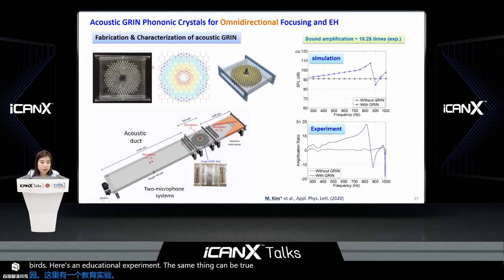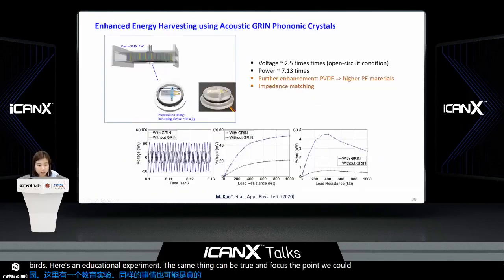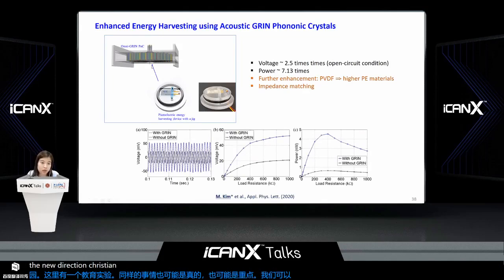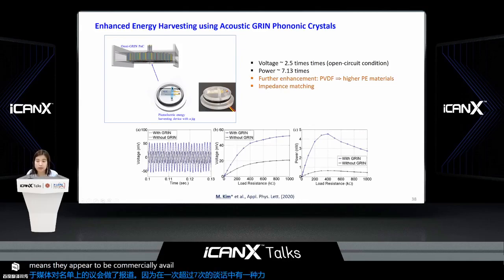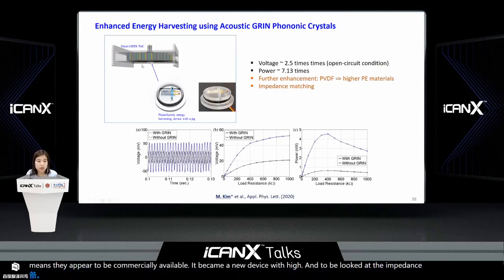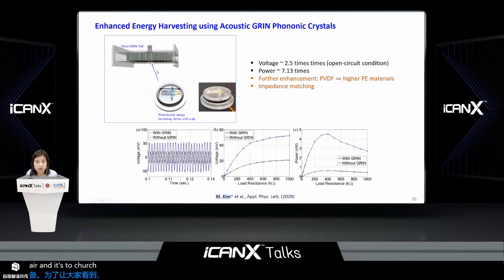And at the focused point, we tried to characterize the harvesting performance using these omnidirectional phononic crystals. So we located the PVDF, the piezoelectric polymer film, on the bottom of the omnidirectional phononic crystals, and we found that there's a power enhancement of up to more than 7 times. And since we use the commercially available piezoelectric polymer film, if you use a device with high performance piezoelectric material, there's room for further enhancement. And if we look at the impedance matching between the air, the sound, and the structure, then we can further improve the energy harvesting performance using these omnidirectional phononic crystals as well. That was about the sound energy harvesting.